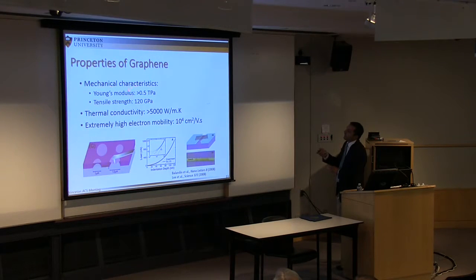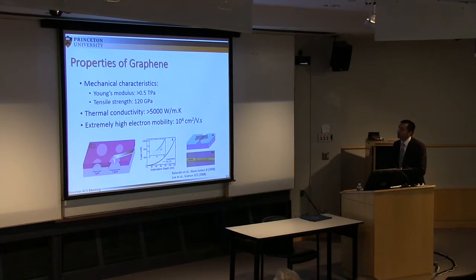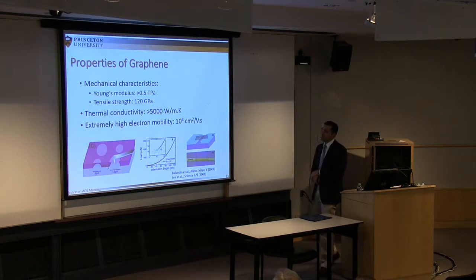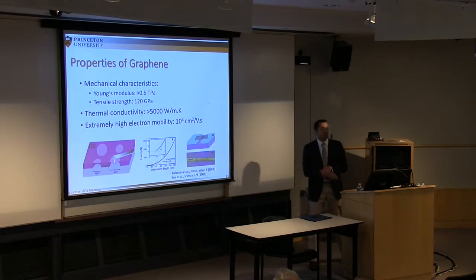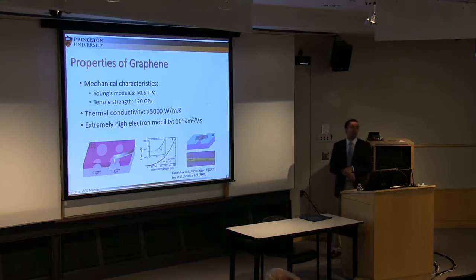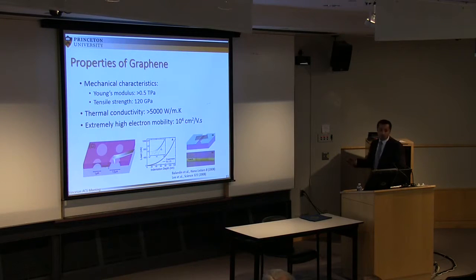It turns out that a group at Columbia recently measured a modulus as high as 0.5 terapascal. If you go to ab initio calculations, the predictions even go up to 1 terapascal. So this is way higher than any steel. And the tensile strength is also impressively high, 120 GPa. So it's following kind of the same trend.